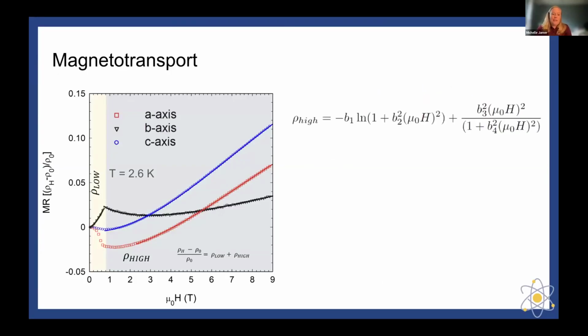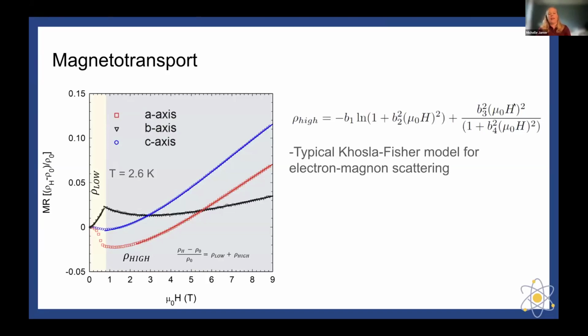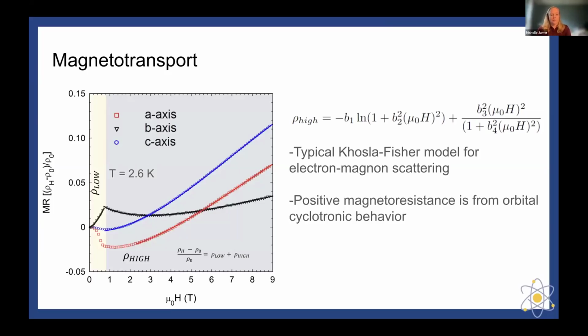For the high field, it behaves similar to how all metals behave, which is an electron-magnon contribution, which was first published by Khosla-Fisher. And what we see here is that it is electron-magnon scattering. We have terms that are also proportional to the applied field, mu naught H squared, and that is going to be related to the mobility of the material. So the positive magnetoresistance along the A and the C axis in particular, and along the B axis at high field, is just typical orbital cyclotronic behavior of metals.